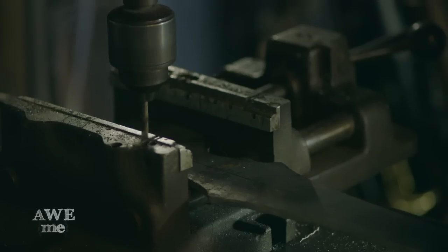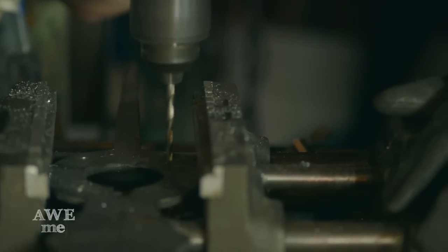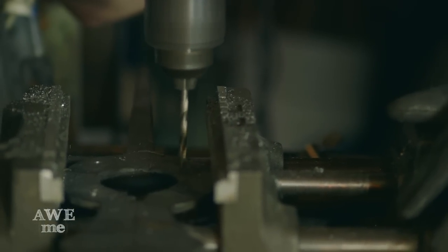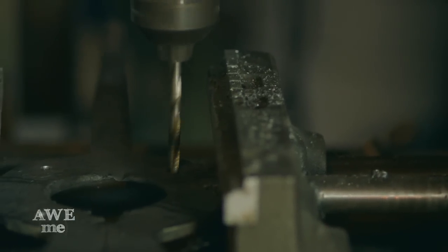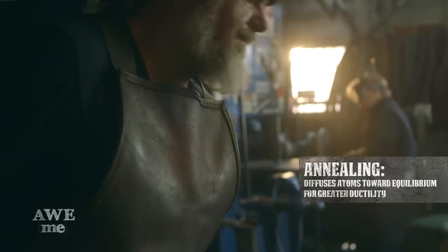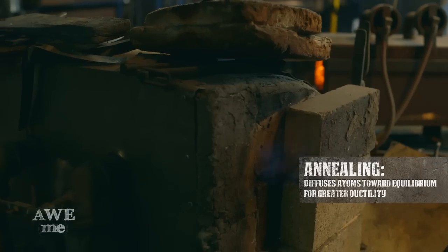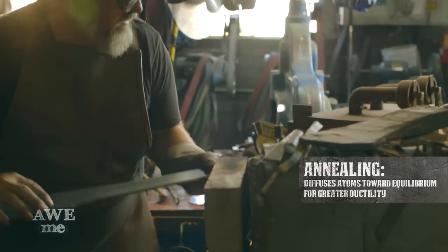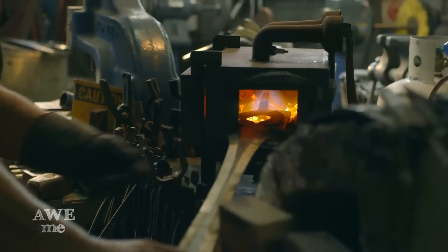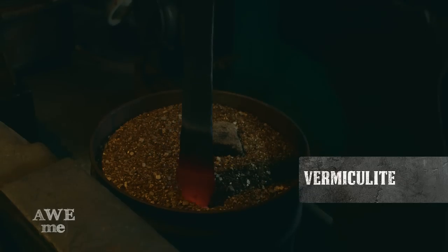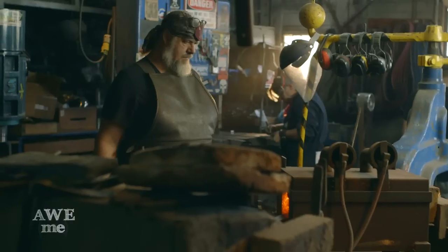After Bryan had drilled the 3 holes to attach the aluminum donuts, there's one section of the 5160 steel blade that was still too hard, so we had to anneal the hilt. Annealing is a process where we heat it up to the critical temperature, which is about 1500 to 1600 degrees, and then put it into vermiculite, which is like an expanded mica, to allow it to slow cool so that a regular drill bit would be able to drill through the metal.